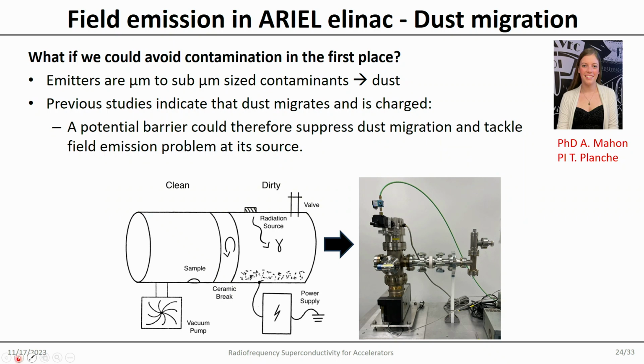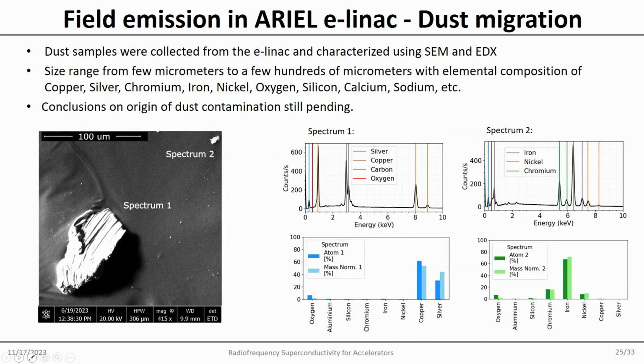So what we know is that the emitters are micrometer sized to submicrometer sized. It's basically dust. Yeah? What we know is also that previous studies say that it's apparently charged. Okay, there are many elements in there which could cause that. But if it's charged, and we know which way, whether it's positively or negatively charged, this dust, we could potentially use a DC, basically a barrier, a voltage, yeah, to prevent it from happening again. This is what Alvin's project is about. She tried to find a way how we can really avoid field emission in the first place.